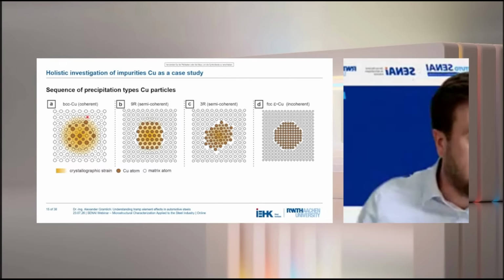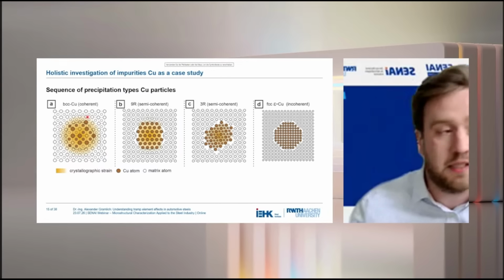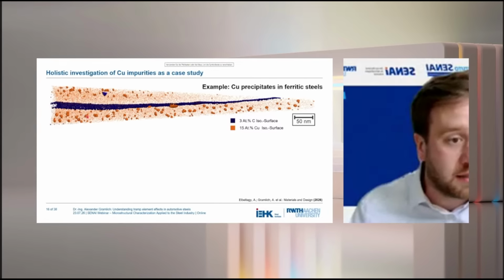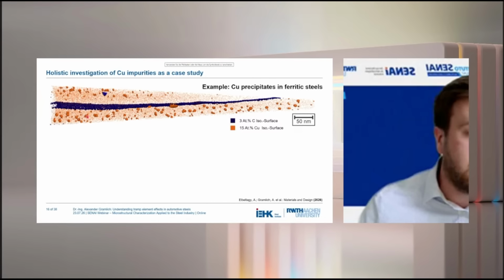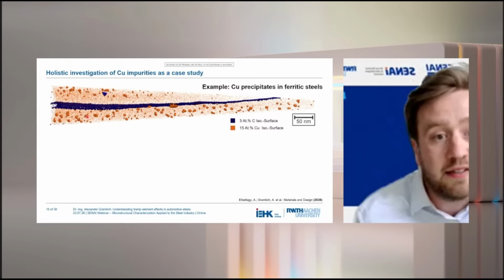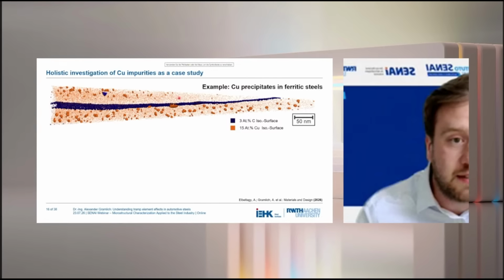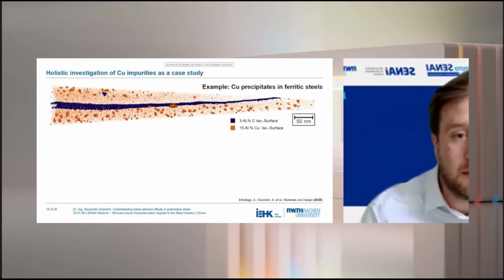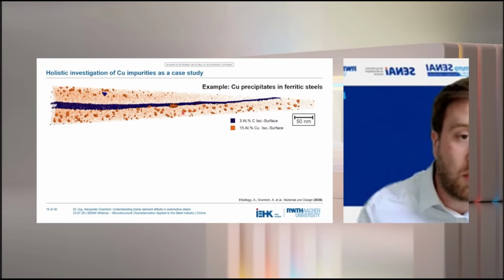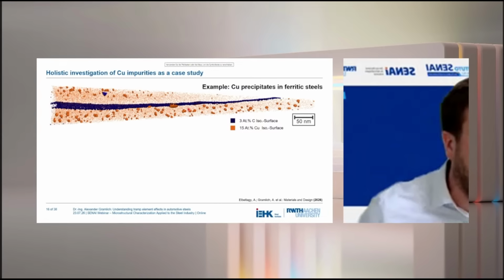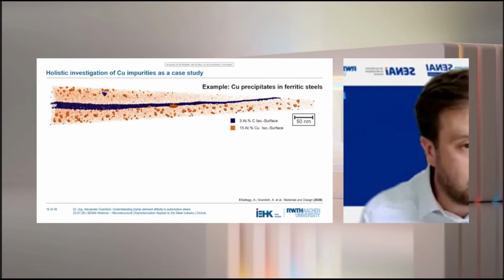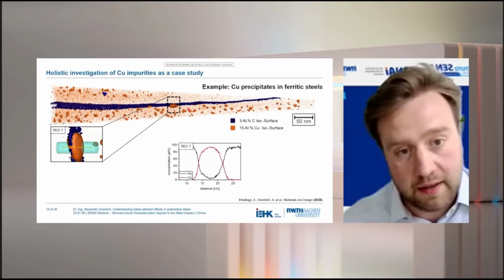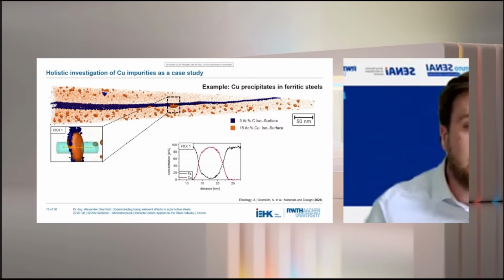This is only schematic, but as Anderson also nicely pointed out, we nowadays have possibilities to investigate copper at atomic resolution. And this is what we did in the past. So here you can see an atom probe tomography result. Basically, all these small orange dots you can see here are single copper atoms. And with these larger orange balls, we try to visualize copper precipitates. You can do more. You can go very much into the material and investigate these precipitates also chemically.